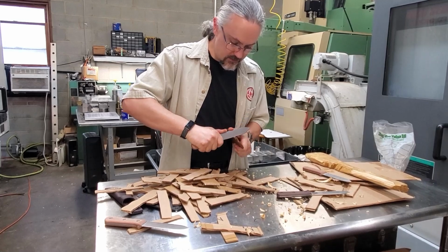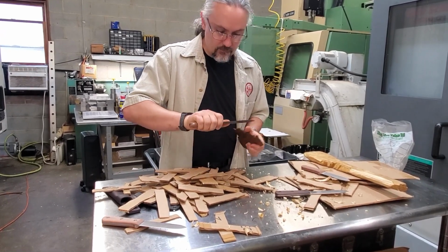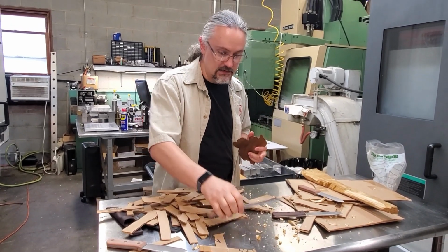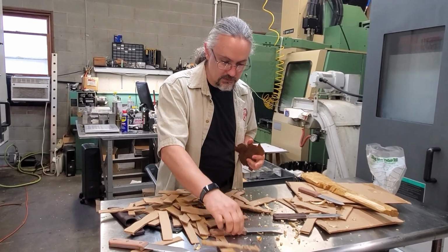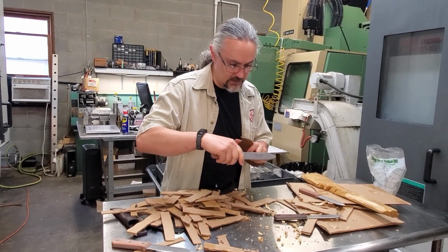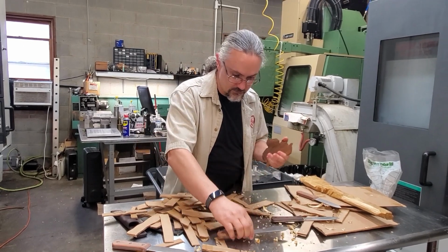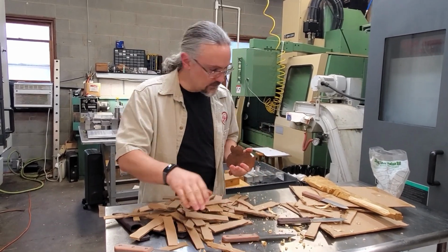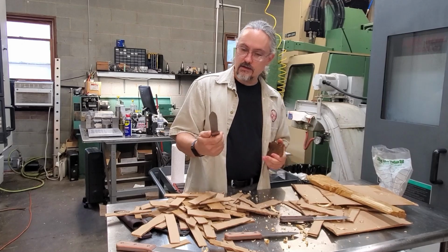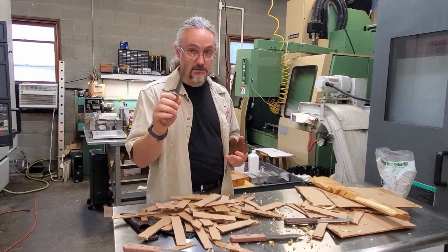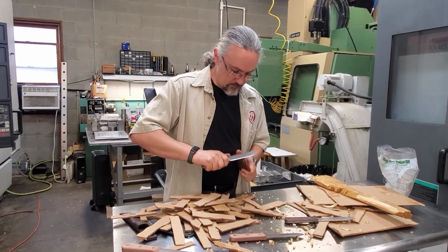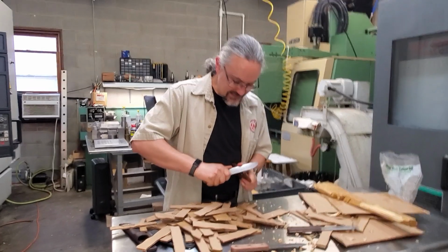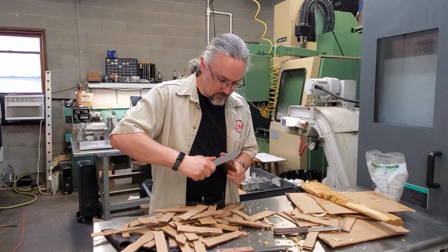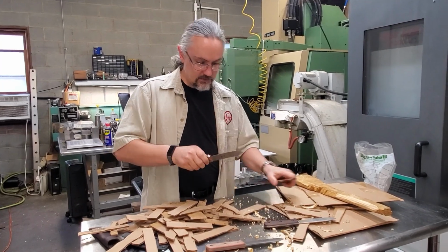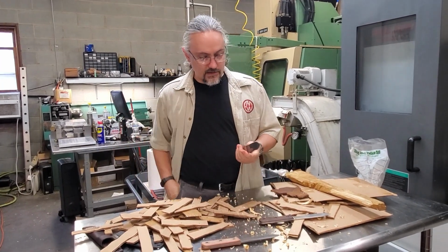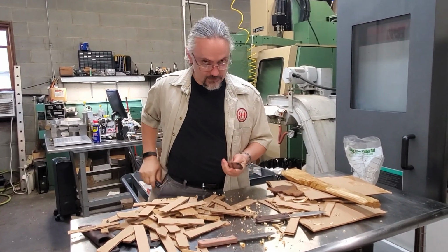So this cut right here plays hell on any steel that has issues with edge stability. And so the Delta heat treat right here, which I can already tell you is perfect because we've done this a bunch of times, the Delta heat treat does really well. And then this guy right here, which is the standard heat treat, uses the secondary hardening hump. It will have inferior edge stability in this kind of use where you're putting it in something really hard like this and peeling it. And so if I look at this under magnification and I hit it with a flashlight, I'm going to see some trouble there.